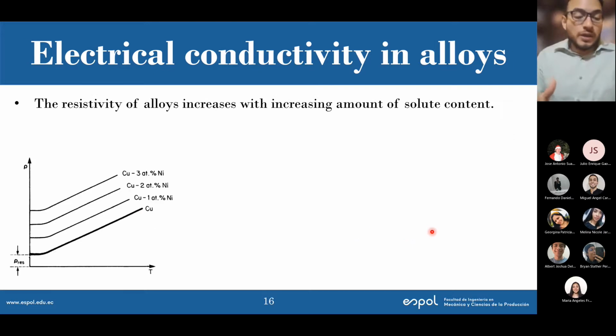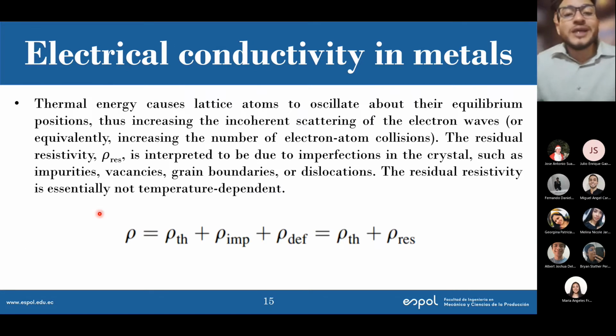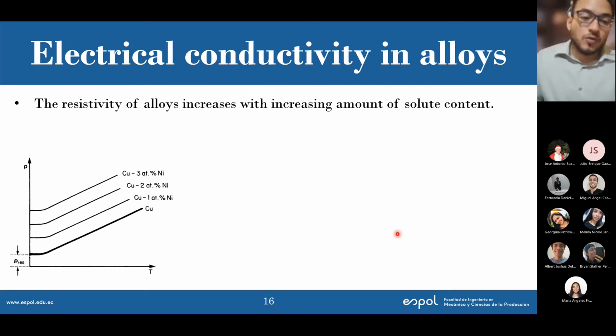Then the resistivity increases, and that's why you see that the residual resistivity is increasing. So this is for pure copper. If I have copper nickel 1%, then my residual resistivity will go here, and that's something important. This term is temperature dependent, but not solute dependent. This term is temperature independent, but it's solute dependent. So the more solute I put, the higher the residual resistivity.